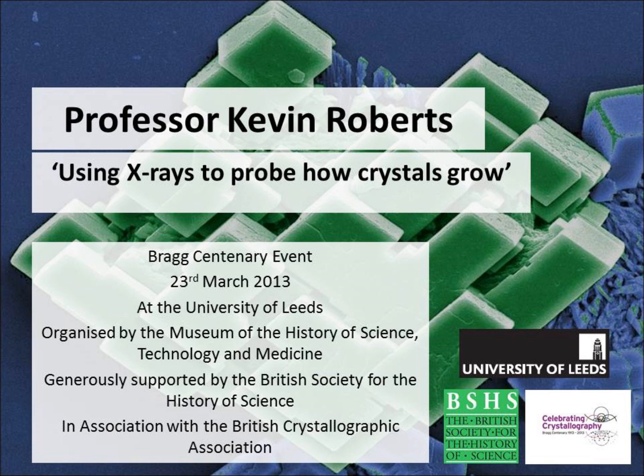Similar here. This is a crystal, the same crystal, now at the surface of the crystal. Look at all these, you see all these little etch pits coming through where the crystal, after washing, has been a bit thinner. These are so-called pendellösung fringes that you get in that. And then here's a bunch in the middle. And these are all the dislocations that come. I think I hold the world record for ammonium sulfate pictures. This is ammonium sulfate, which is an agrochemical, an intermediate. Just wanted you to have a look at some of these beautiful dislocations that you get through the material.